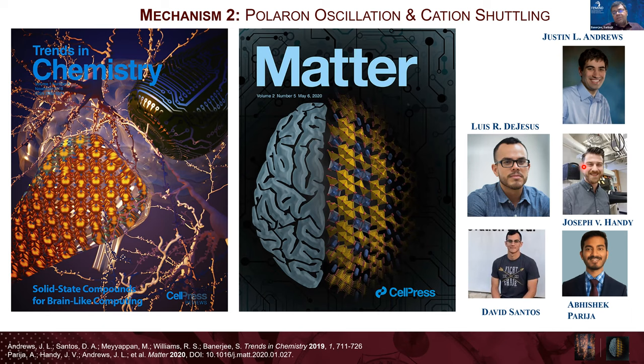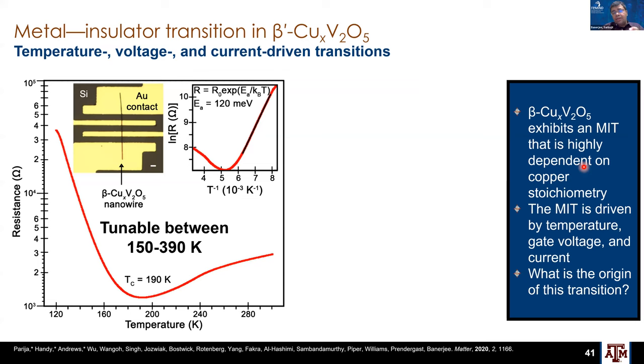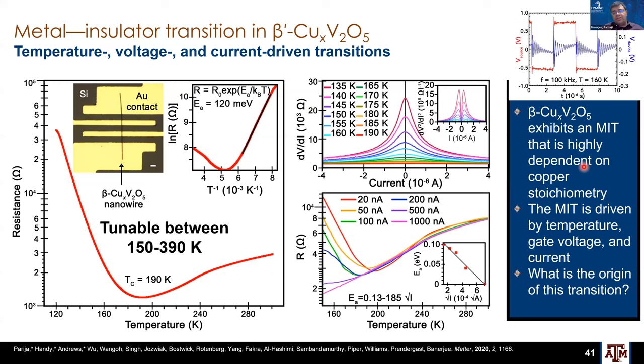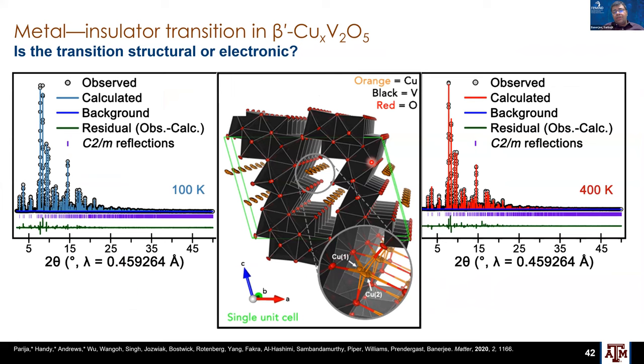Across a neuromorphic transition. So we took beta prime copper V2O5. We can grow nanowires, but we can also grow single crystals of these. And it's a beautiful system, not as sharp as VO2, but 150 to 390 Kelvin. You can get voltage and current induced transformations. And what we can do is single crystal diffraction as a function of temperature, and we can see what happens.